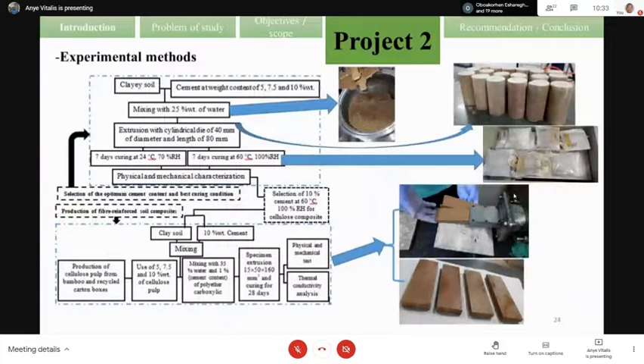Before starting the main study, we determined the optimal stabilization that can help to improve the mechanical and physical properties. We varied the stabilizer content from 5 to 10%, and also varied the curing condition with 24 and 60 degrees. We produced cylindrical samples and applied compressive strength, water absorption, and porosity tests.